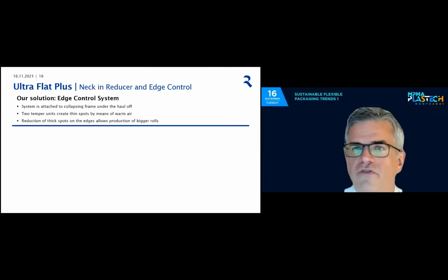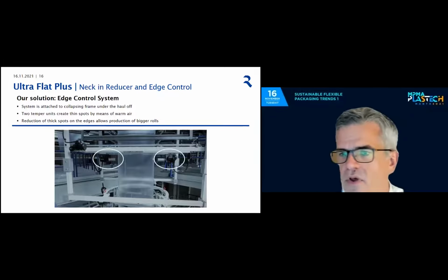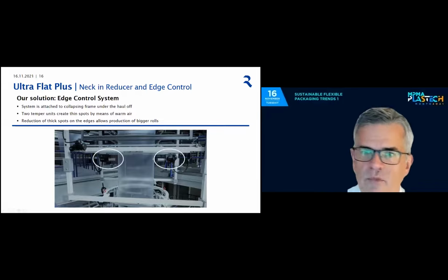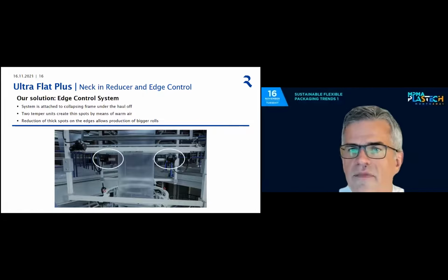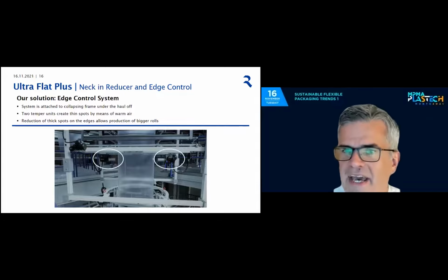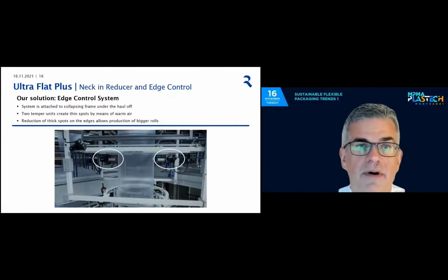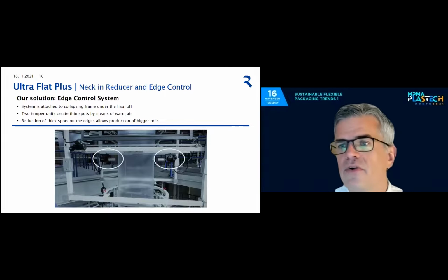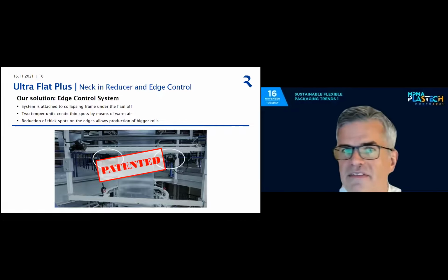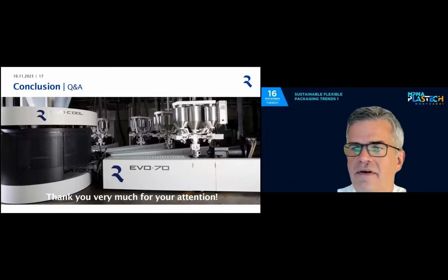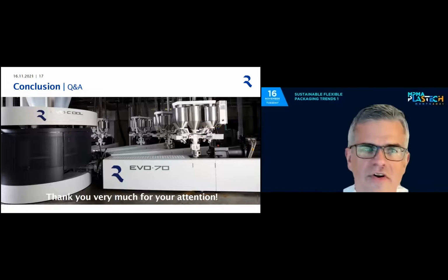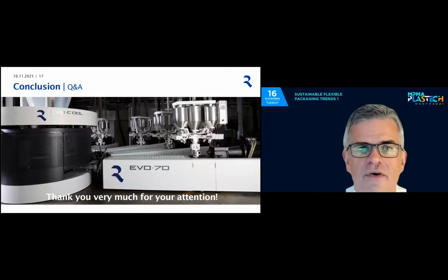And we found a solution for that, which we call the edge control system, where we apply some heat just before the collapsing frame under the haul-off, where we warm up the edges of the film and, by doing so, reduce the thick spots at the edges. And by doing so, we can realize big rolls of material by reducing this thick edge, the bone effect. And with this comment on a solution for the thick edges for stretched tube film, I would like to close my presentation and say thank you again for your attention.